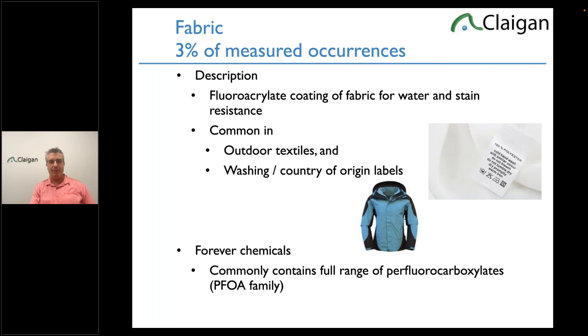Fluoroacrylates have one weak carbon-oxygen bond. Fluoroacrylate-coated fabric — whether it's an outdoor jacket or that washing instructions label — contains the entire PFOA family. A large portion of all clothing in Europe may be non-compliant right now because of that label, and suppliers haven't added PFOA directly — they added fluoroacrylate, which breaks down into PFOA.